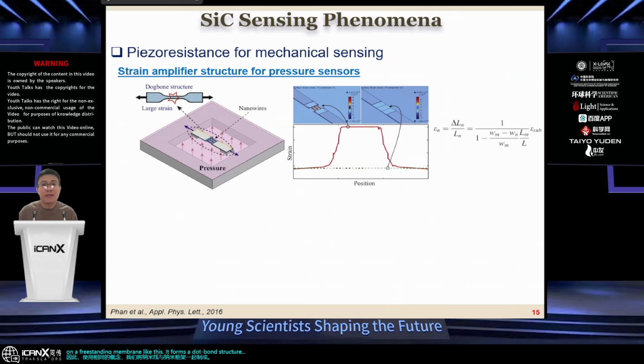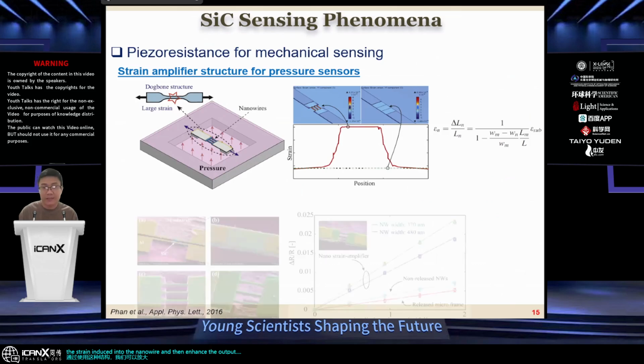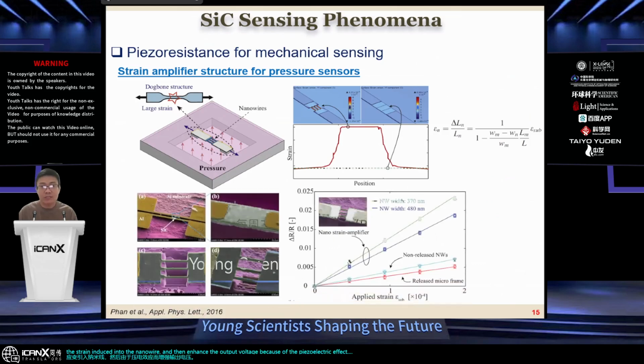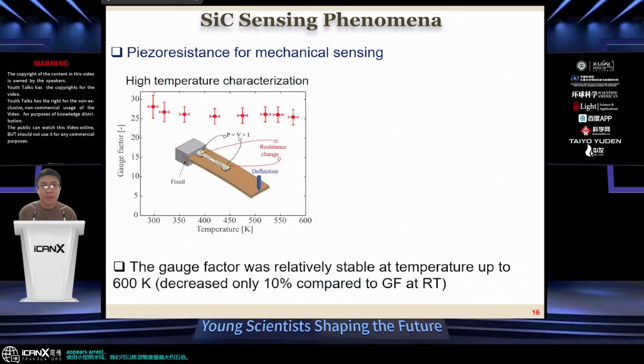So when the membrane deflects, more strain will be concentrated on the narrow area, which is the nanowire here. And by using this structure, we can amplify the strain induced into the nanowire and then enhance the output voltage because of the piezoresistive effect. And we demonstrate the concept using focused ion beam to make the nanowire here. And using a small nanowire, we can enhance the sensitivity by around 5 times compared to the bulk silicon carbide piezoresistor.